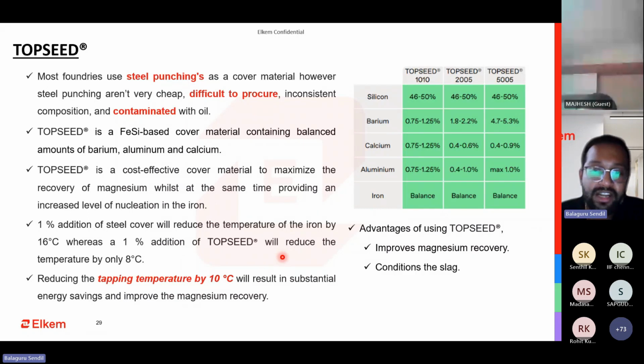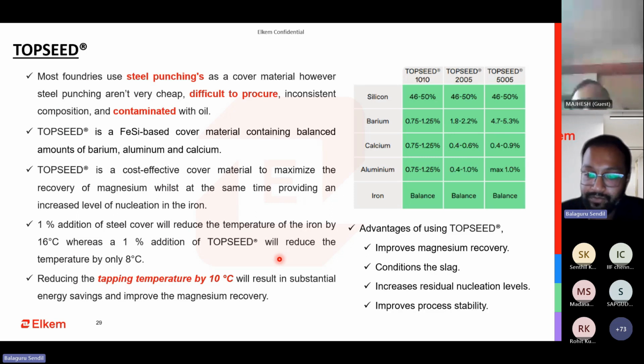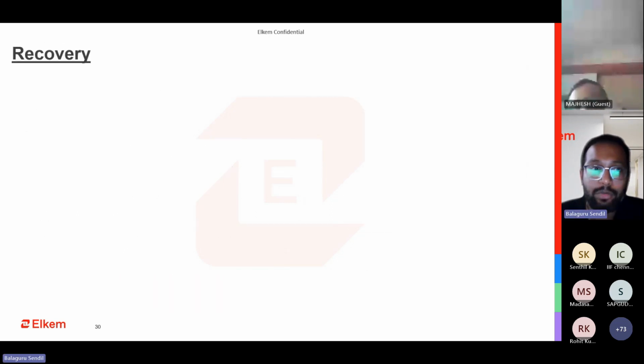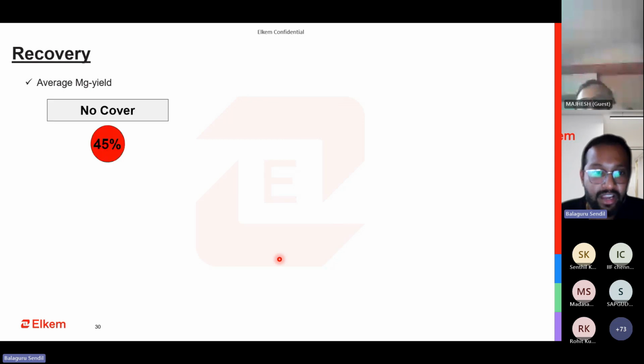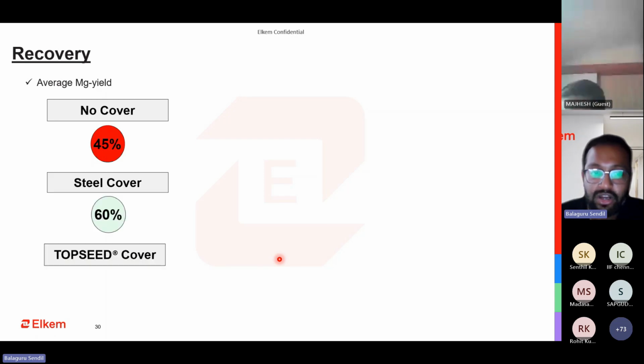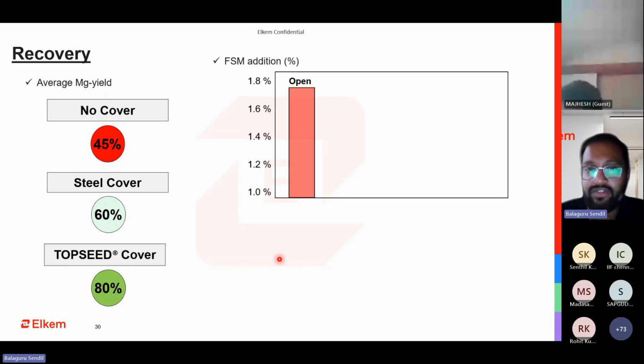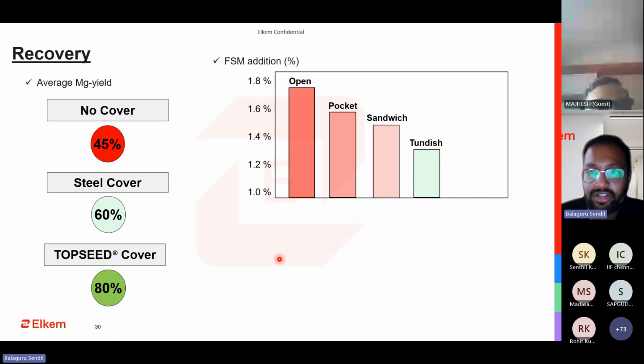And most importantly, it conditions the slag. You'll be able to remove the slag very easily, and it makes your process more stable. When it comes to the recovery part of it, without cover you have only 45%, just open treatment. If you're using some sort of a steel cover, you'll get 60%. With Top Seed, it is always greater than 80%. So this is very realistic data that we have generated. With FeSiMg, as I said earlier, open treatment 1.8; you put a pocket, a sandwich, a tundish, and with Top Seed it is always less than 1.